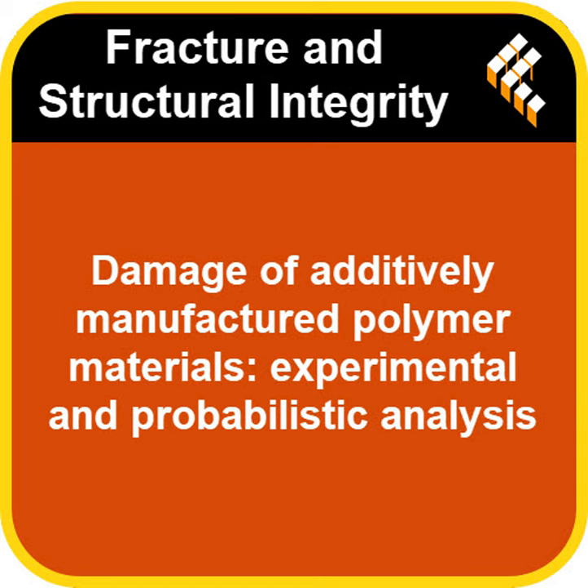Okay. And finally, based on all this understanding of how cracks grow, and especially when damage becomes uncontrollable, pinpointing that 50% life fraction threshold, they proposed a very targeted, proactive solution. This was really neat. They suggest that if a crack in a 3D printed PLA part reaches around 45% of its width, so just before that critical value at 0.5 where unstable failure really kicks in. Exactly, before it hits the uncontrollable stage. They suggest you could intervene. Intervene, how? Just stop using the part?